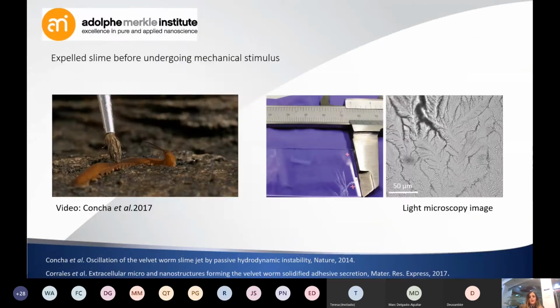So part of the work we have been doing here was studying this material. Why this material? Because it's a unique material that is natural and is mechanoresponsive. So you take this slime and you leave it on a surface for 24 hours, and it stays liquid. It's like a droplet. But you touch it, and immediately, in 10 seconds, it's harder. It hardens with the mechanical resistance of nylon.